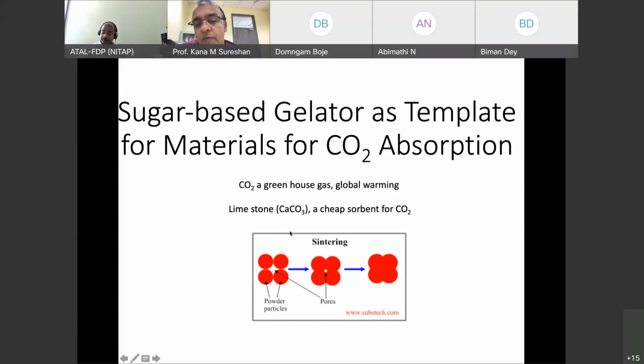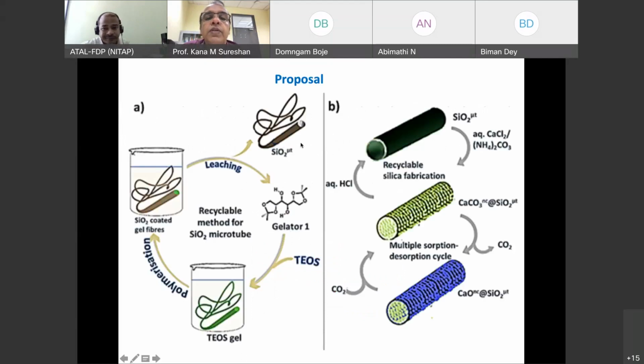So ideally what we want is to increase the surface area of calcium oxide. We thought we could use our gel chemistry. How do we do that? Here, this is the gelator. TEOS, tetraethoxysilane, is a solvent which can form a gel. Also, if you hydrolyze tetraethoxysilane, you will get silicon dioxide, silica. So this is a precursor for silica, and also a gelling solvent. So we made a gel out of this one.